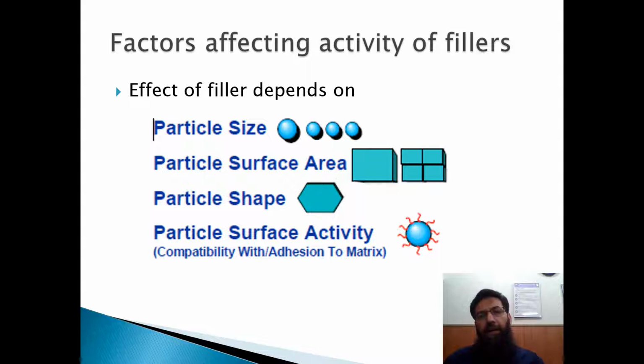The surface area can be enhanced by different surface treatment methods, which are available for different kinds of fillers. Then particle shape is also a very important criterion, because there are different fillers which are present in a particulate-like nature, and different fillers which are present in a plate-like nature. Calcium carbonate, carbon black, and silica are particulate fillers. Their shape is spherical, whereas the kaolin clays are present in a plate-like structure.